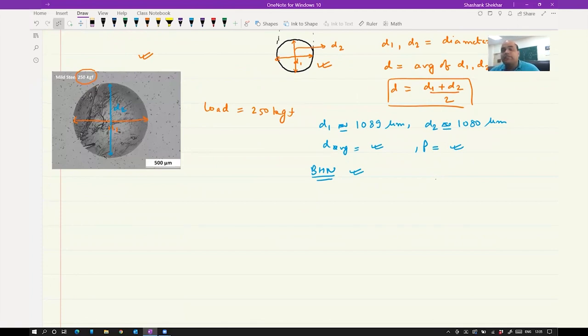Especially when you use a steel ball, the Brinell hardness number is not going to be accurate when your material is very, very hard. Because you are using a steel ball, there is a chance that the steel ball itself is deforming. So if your material is hard, it is better to use Vickers, which I'm going to talk about. There we use a diamond indenter, and diamond itself is very, very hard. So Brinell hardness is not reliable at very high hardness values, that means for a harder material.